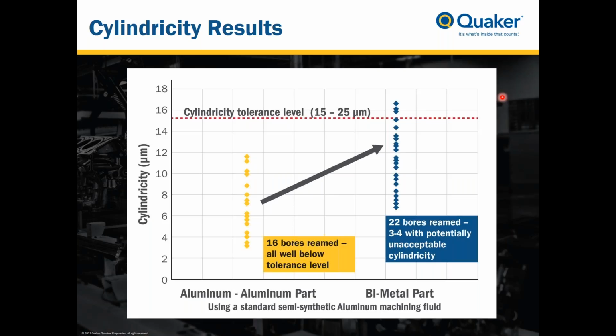And here's the results that we obtained, and I'll just talk a little bit about this graph. What's shown on the y-axis is the cylindricity measured in microns. What's shown on the x-axis is the results of numerous holes reamed for both the aluminum part and also a bimetal part, again, which is an aluminum 356 and a powdered metal bearing cap. And for the aluminum part, you see the data points for 16 bores that were reamed. And what you can see is that they're all down below a cylindricity of 12 microns.